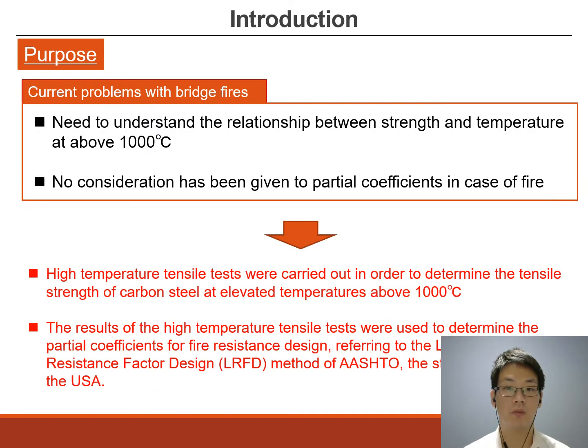Therefore, reliability indexes, load factors, and resistance coefficients were studied with the aim of clarifying the resistance coefficients under fire conditions. However, in these studies, the partial coefficients for fire have not been considered. The current problems of bridge fire are as shown in the previous slide. In order to solve these problems, high temperature tensile tests were carried out in order to clarify the mechanical properties of carbon steel at temperatures above 1,000 degrees. Based on the result, the partial coefficients were obtained by referring to the load and resistance factor design method of AASHTO.